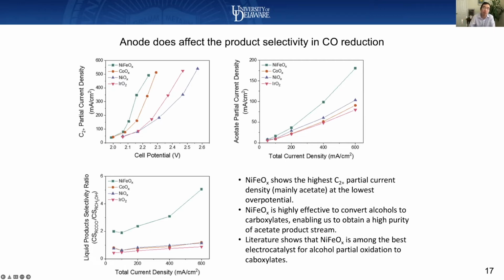So then we looked into the literature trying to prove our concept. Our suspicion, which is a reasonable suspicion, is that nickel iron oxide turns out to be a highly effective catalyst for partial oxidation of alcohol to carboxylates. This actually is kind of a proof of what's going on in our system: you generate alcohol at the cathode, and when the alcohol diffuses to the anode, it gets partially oxidized into acetate. That's why you have a higher acetate selectivity, but almost no alcohol at all.